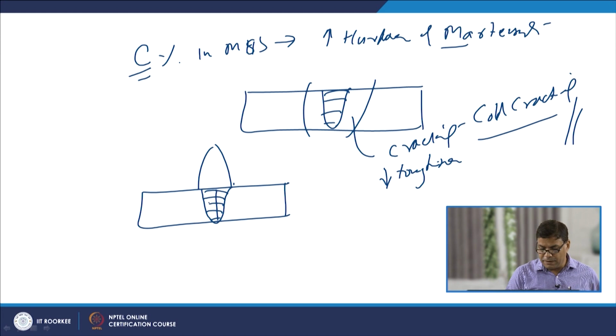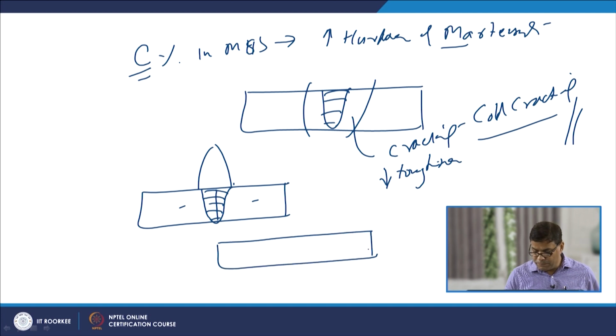Matching filler means the weld metal is similar to that of the base metal. When the autogenous weld is being made, then just a fusion of the faying surface is realized, and subsequently, on solidification, we get the weld joint. So, in both cases the chemical composition of the weld metal is similar to that of the base metal, and that is why it promotes the cracking tendency, and the properties of the weld metal and the heat affected zone will respond in almost the same way.